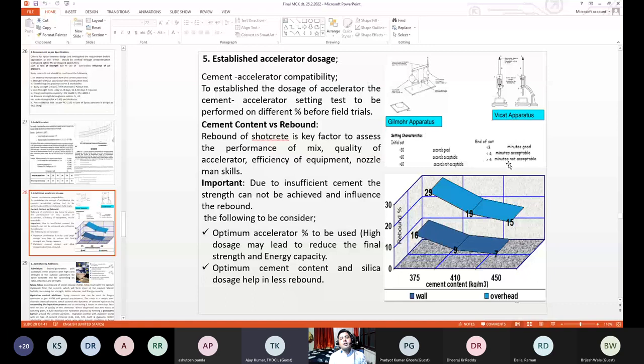The cement content versus rebound. Rebound of shotcrete is a key factor to assess the performance of the mix, quality of accelerator, efficiency of equipment, and nozzleman skill. They all work together, then you may achieve good results. Due to insufficient cement, the strength cannot be achieved and it influences the rebound. The following to be considered: optimum accelerator to be used, high doses may lead to reduced final strength, and optimum cement content and silica doses help in less rebound.